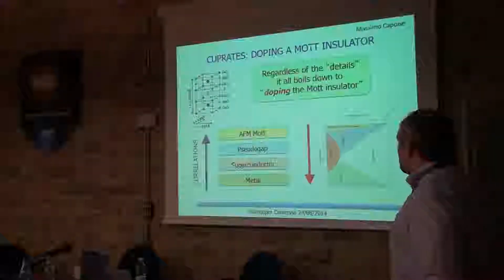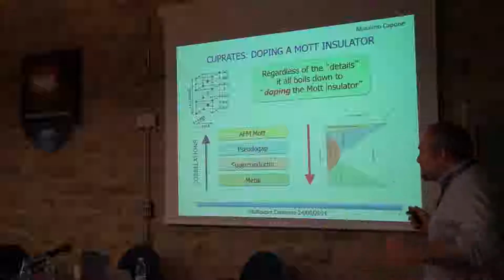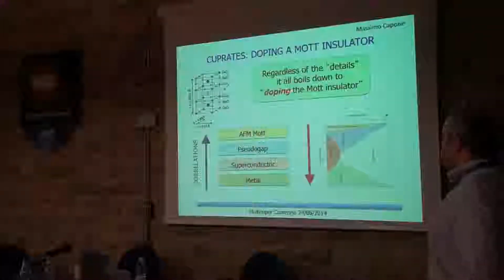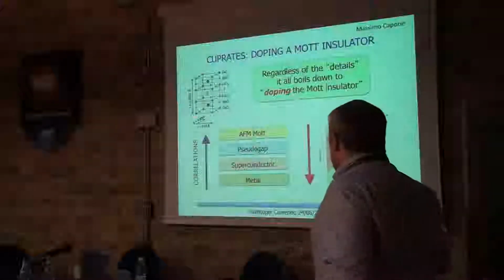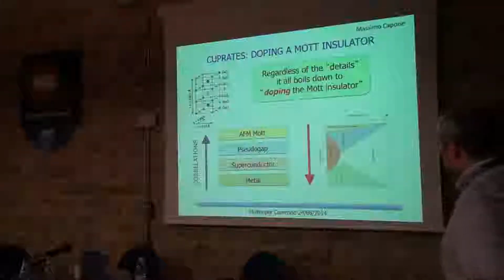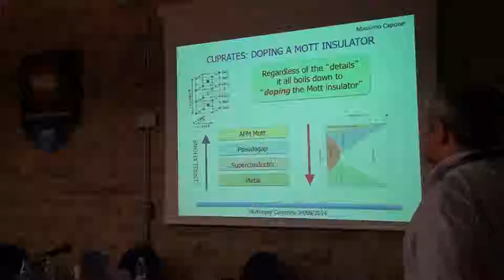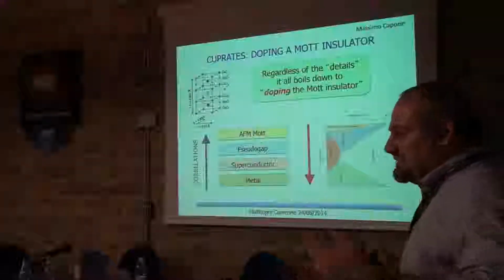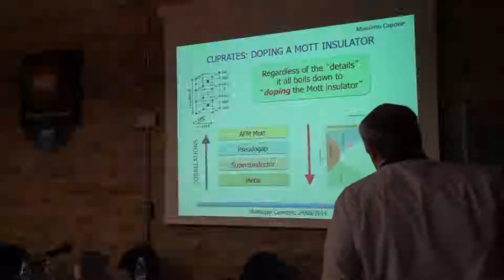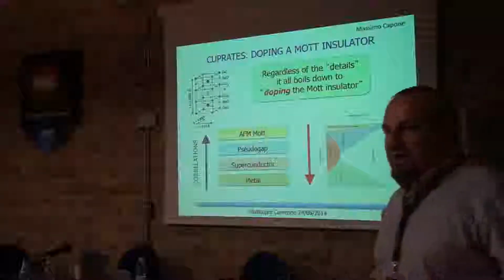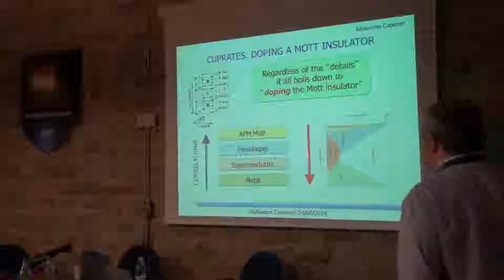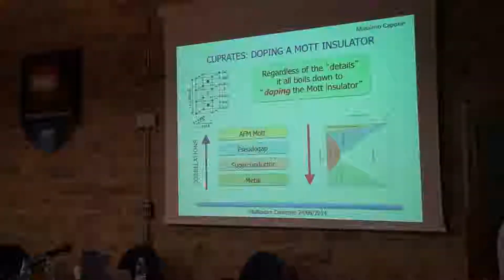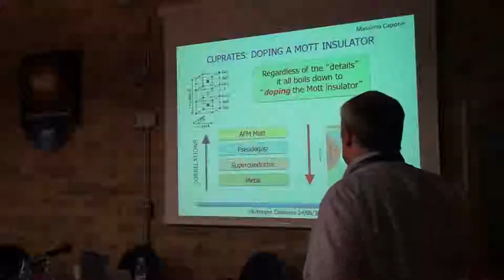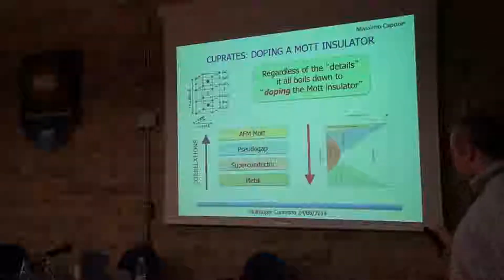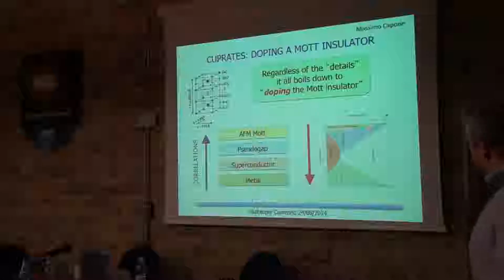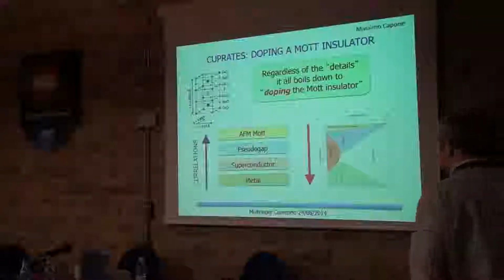So, there is one bottom line to describe the way you may look at the phase diagram of high-temperature superconductors, of the cuprates, which is that everything boils down to doping a Mott insulator. It's a sideways phase diagram, just for graphical reasons. You go from this antiferromagnetic Mott state, you dope it, and you get into the famous pseudo-gap region, then you have the superconductor, and finally you get something which looks like a normal metal in the overdoped region. This is something very well known, and it mirrors a decrease of the role of electron-electron correlations, which are the thing that makes the Mott state localized, as Sir Mott discovered, and they decrease their impact as we go away from this Mott state.